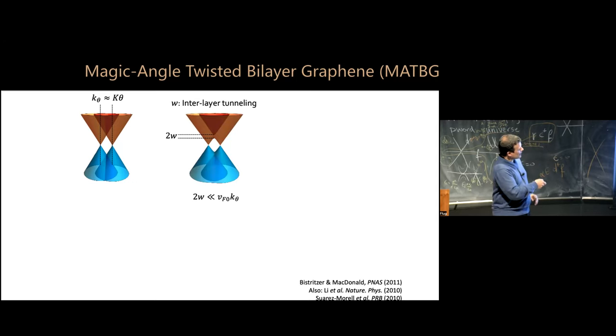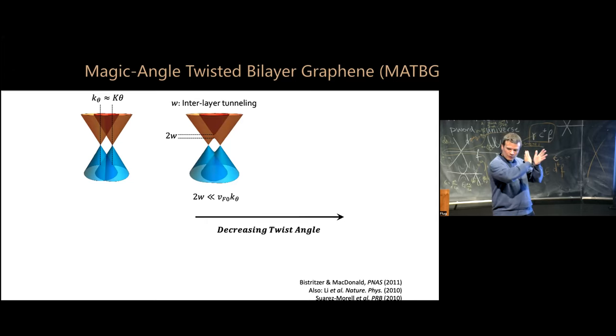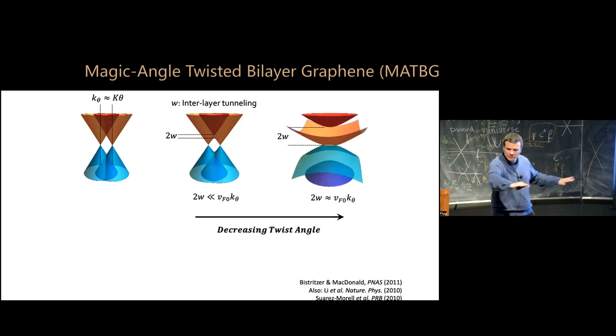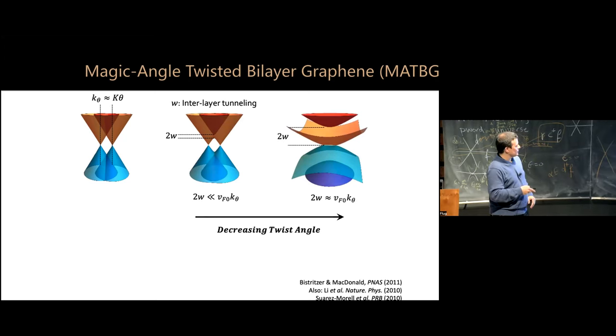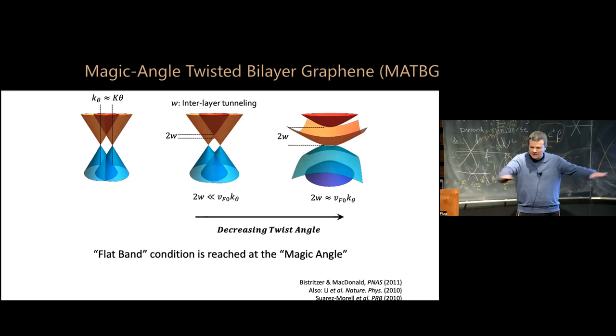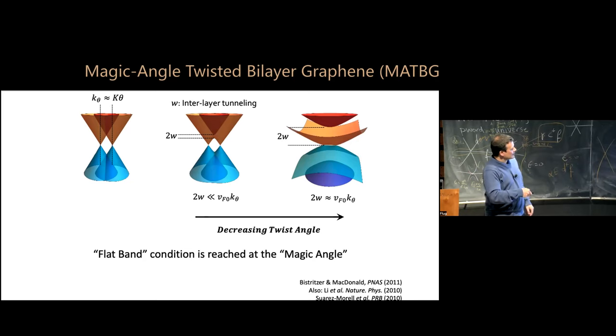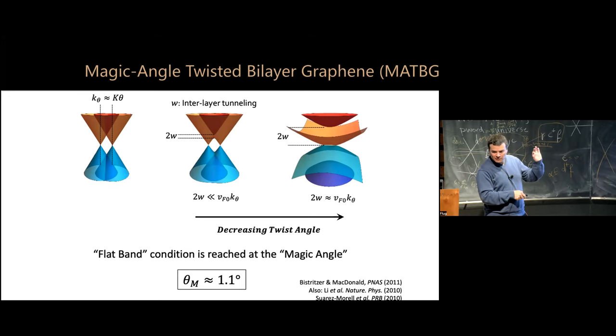So if I decrease the twist angle, now rotate towards smaller and smaller angles, okay? These two cones get closer and closer, and this band repulsion pushes the energy of some of the electrons down all the way to zero. Okay? At that moment, we say that a flat band condition is realized. That means the electrons have zero energy. Okay? And this thing is realized at an angle which is 1.1 degrees, a very precise angle.